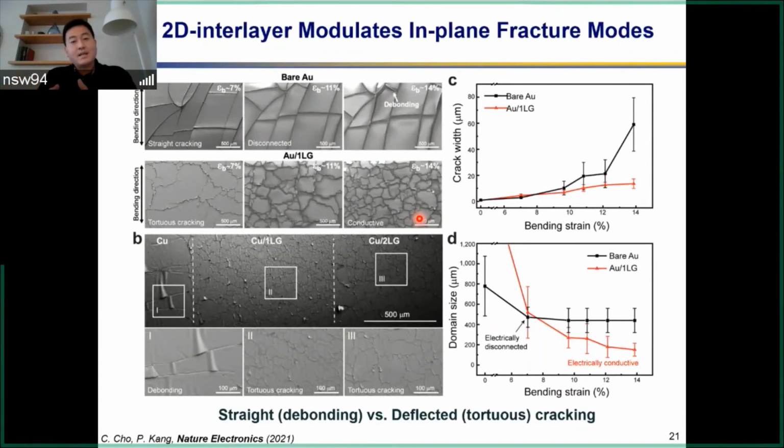So mechanically, this is still fracturing. It's still not completely failed. It's not done, and you don't have nothing. It's still fracturing into smaller pieces. And what's also interesting, and this is what we observed early on electrically, is that if you start to add more layers, the failures start to delay even further. So one layer, two layers, three layers, four layers, it gives us distinctly different electrical responses. So that was also interesting.